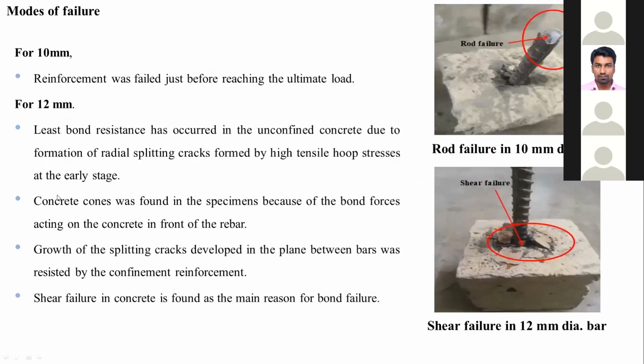In the modes of failure, we found that for 10 mm reinforcement, rod failure occurred, because if you pull out the reinforcement, the rod failed first. That is because of the bond. If we apply load here, the reinforcement fails first, because the bond strength is more than the tensile strength of the reinforcement.